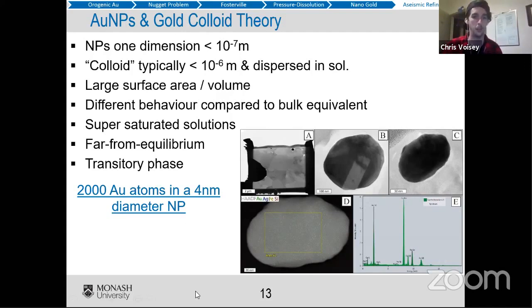But the reason why we're really excited about them is that a 4 nanometer diameter nanoparticle is 2,000 gold atoms. So if you think about traditional fluid chemistry and having one gold atom on one gold ligand, and then having a maximum of, let's say, 1 ppm or so in a fluid, if you can make gold nanoparticles, you can carry a heap more gold in a fluid, at least momentarily, to try to concentrate it in an area. And I think that's why it's so exciting and why we're kind of seeing a bit of a turn towards nanoparticle technology recently in ore deposit studies.